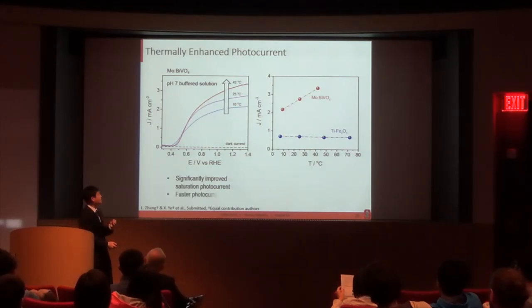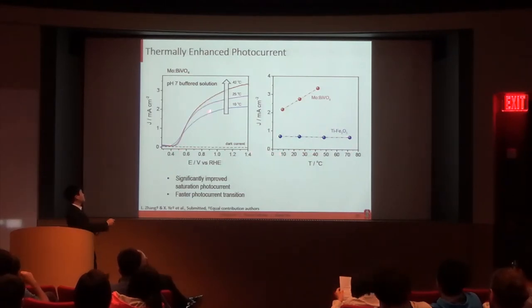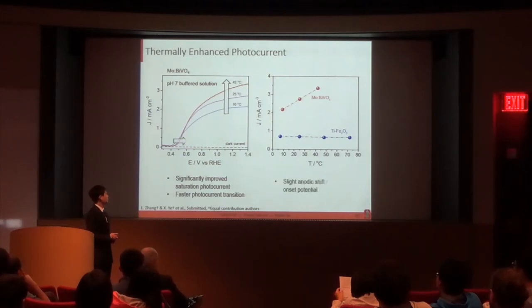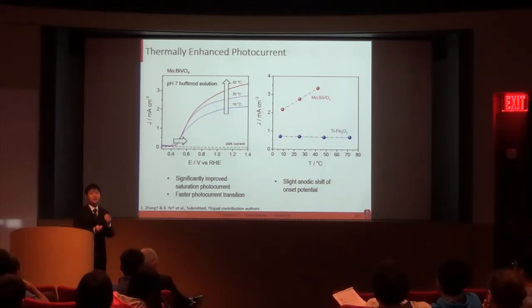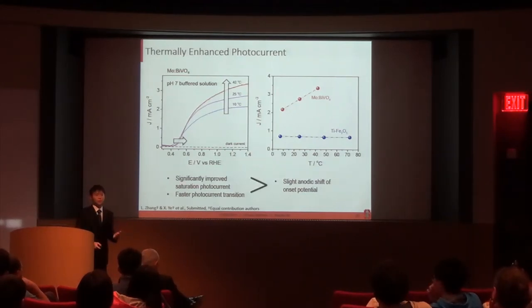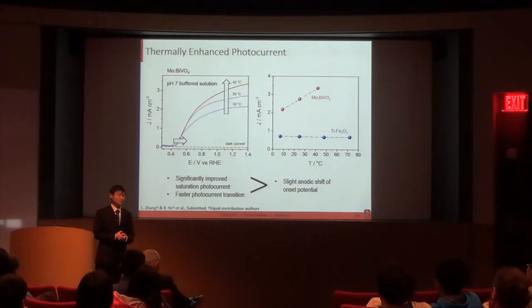And second, as we learned from the hematite photoanode, we also saw this faster photocurrent transition in a BVO photoanode. As for the onset potential, the onset potential only shifts slightly in the anodic direction. So without any quantitative analysis, we can already see that this significantly improved saturation photocurrent plus the faster photocurrent transition already outweighs the slightly anodic shift of onset potential.